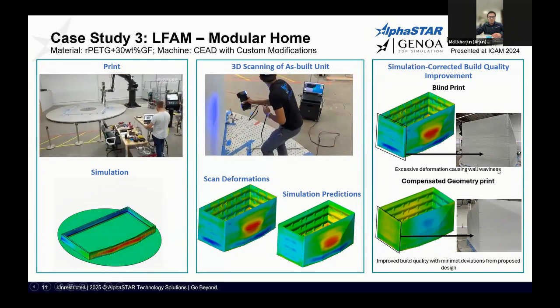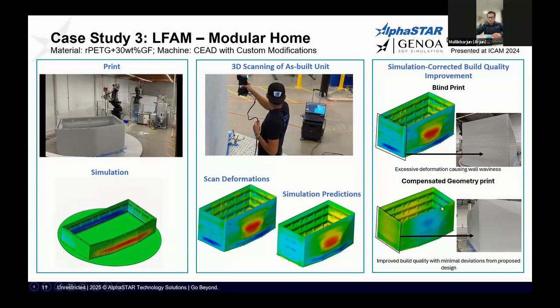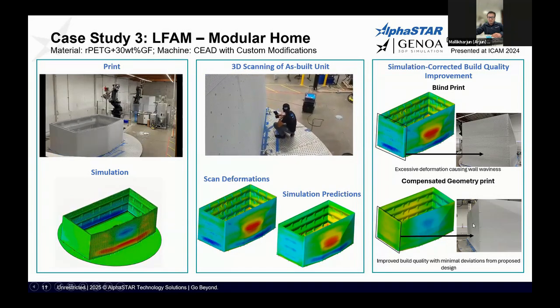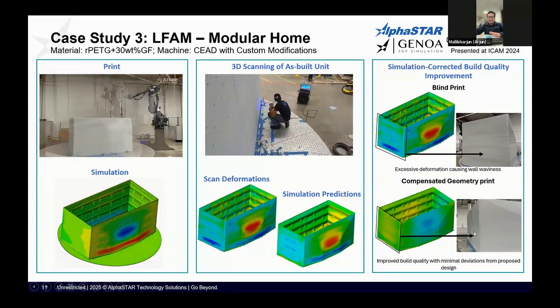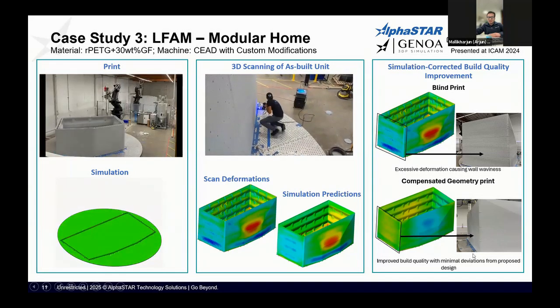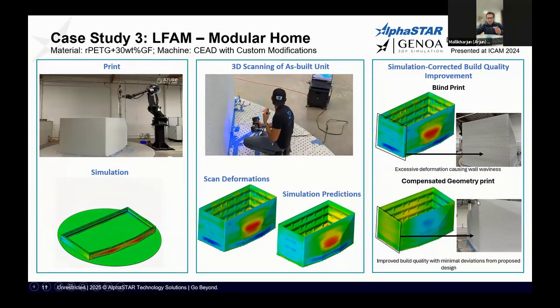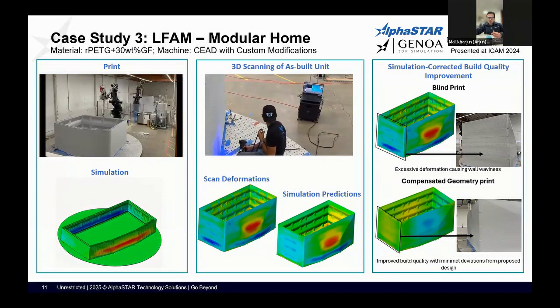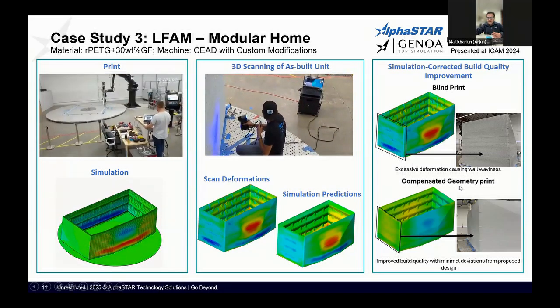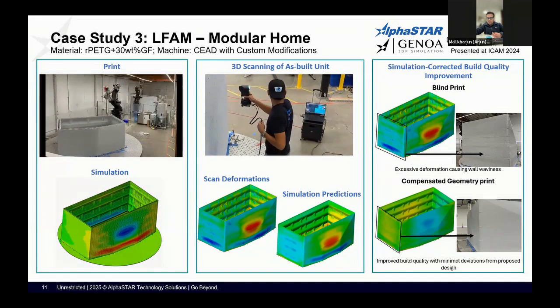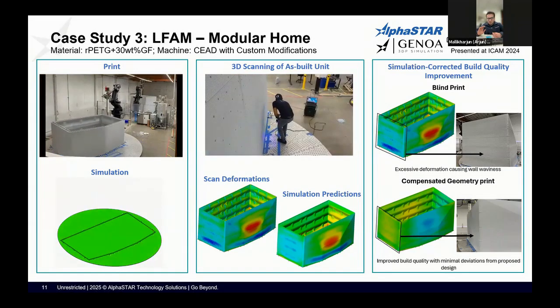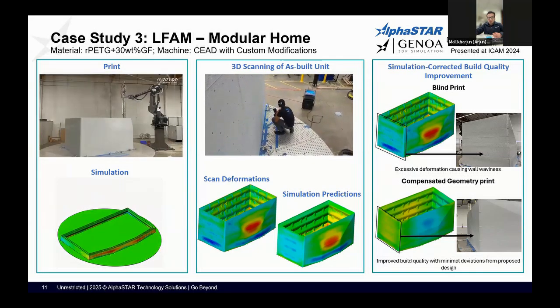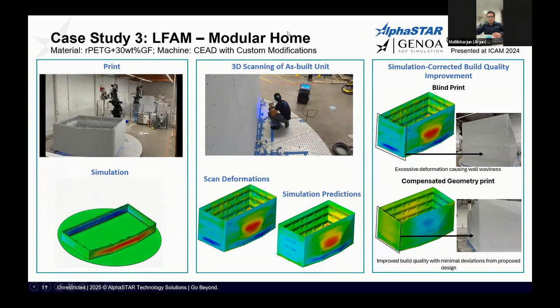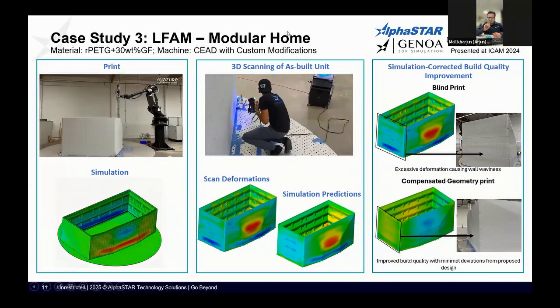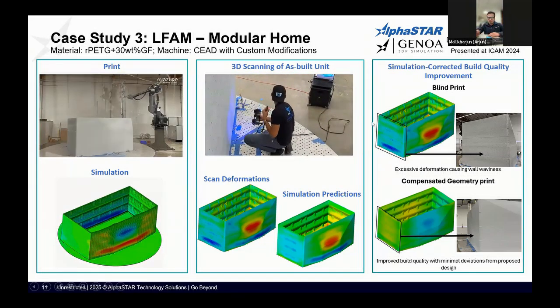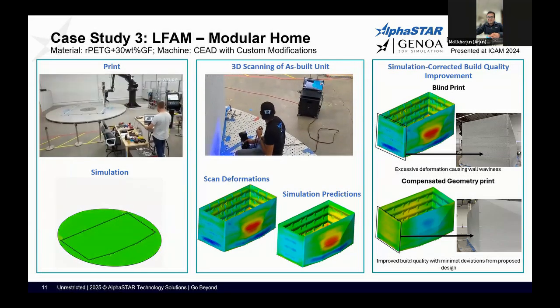Based on simulation, we created the compensated geometry and printed it again. And now with that, we can see the side wall is an 80% to 90% improvement. That waviness is completely gone. Even though there is 1, 2 or 3 millimeter waviness given the structure, it's almost completely flat. And that's the improvement on the side walls. Whereas on the big walls, the roof and the floor sections, the original blind print showed that red spot, which is extremely bowing out where the cross section changes, and also the bottom bowing in. Those are drastically reduced.